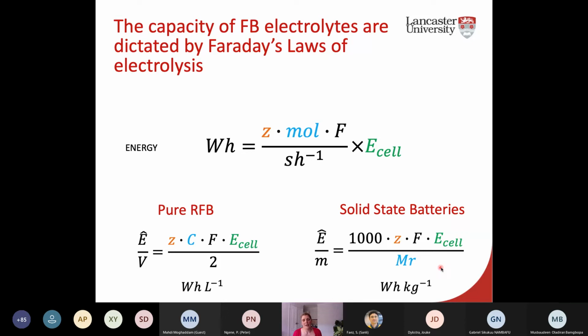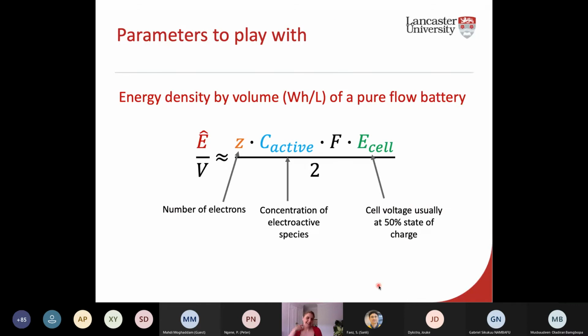For a pure redox flow battery, we end up with watt hours per litre. For a solid state battery, we end up with watt hours per kilogram, and we can convert this one into kilograms if we know the density of the solution, so we can make it relatable. But the key thing here isn't necessarily how those equations are derived, but that this is the critical equation when you're working out what the energy density of your electrolyte is going to be, and how you're going to manipulate that solution to give you the maximum energy density you can get, because that's your main goal initially: to get a really high energy density solution.